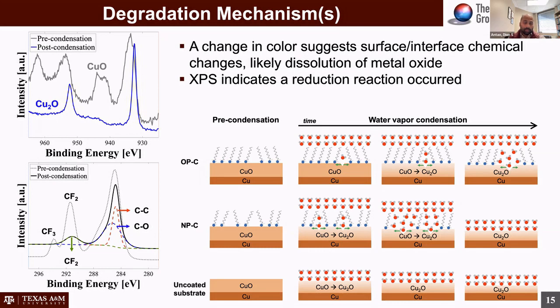We do have this hypothesis for what our mechanism of degradation is, and that is once you have a defect site, you preferentially start to accumulate water in that area. And as water sheds from the surface, the droplets shed from the surface, you bring fresh water to the surface. Keep in mind, the condensate that is formed is deionized water, right? And deionized water is highly reactive. And so you will tend to eat away at the oxide on the surface.